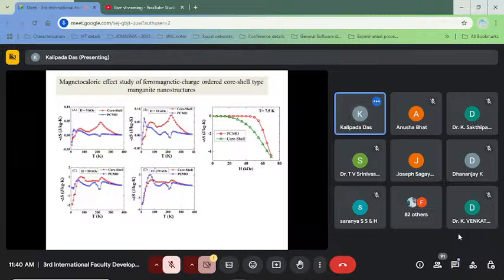So, magnetocaloric effect. The magnetocaloric effect is also enhanced due to the core-shell sample, due to the presence of LSMO and PCMO. A lower value of the magnetocaloric effect is found with respect to the core-shell sample. However, when the magnetic field is very large, that means 70 kilo-oersted, at that time the PCMO nanoparticles are not in the antiferromagnetic phase. They transform into the ferromagnetic one and get a slightly larger value of the magnetocaloric effect with respect to the core-shell sample.